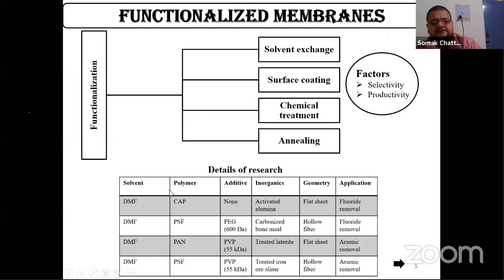And the inorganics that we used for fabricating these mixed organic membranes were many. For DMF and cellulose acetate phthalate, we used an inorganic called activated alumina. For DMF and PSF, we used carbonized bone meal. For DMF and PAN, we used treated laterite. And for DMF and PSF, we used treated iron ore slime. The geometries were also varied. The first one was flat sheet, the second one was hollow fiber, the third one was again a flat sheet, and the fourth one again a hollow fiber. And we used these mainly for fluoride and arsenic removal.